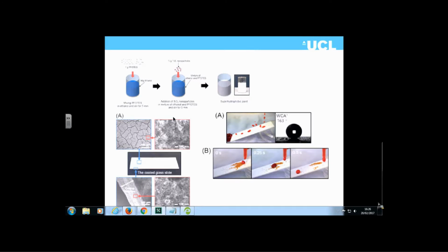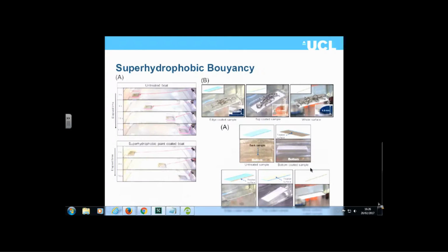Some other applications for these surfaces include developing superhydrophobic paint. We've made some superhydrophobic paint with various mixtures, made with titanium dioxide and a fluorinated hydrocarbon, which when combined give a paint we can apply to a surface to make it superhydrophobic. This generates water contact angles of about 160 degrees, and here's an example of water rolling across the surface and picking up dirt and bacteria.